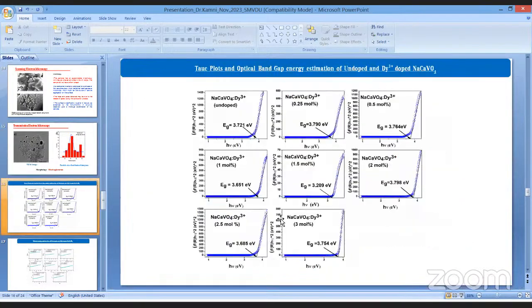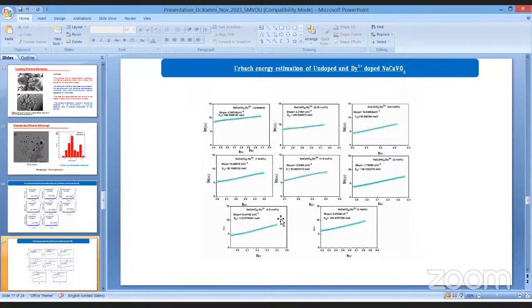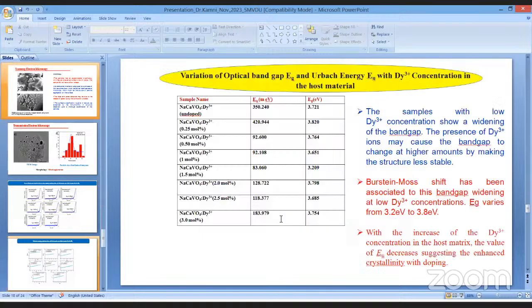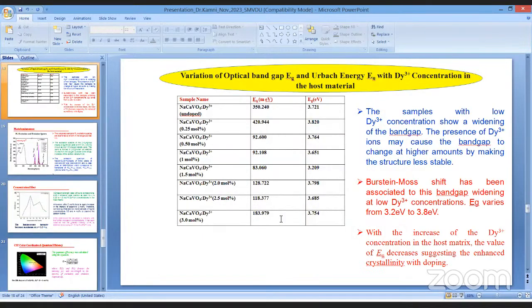histogram. So these are the Tauc plots which are used to calculate the band gap of the as-synthesized nanophosphors, and this is the Urbach energy calculation of the undoped and dysprosium doped nanophosphors. As you can see here, this table shows the name of the sample, from undoped to doped up to 3 mole%. Then we have also calculated for each sample the band gap as well as the Urbach energy.